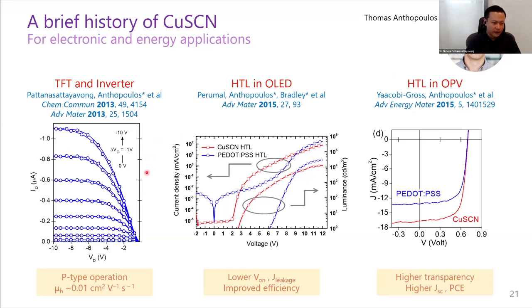It shows a very good field effect, can be used in thin film transistors, and also basic circuit components. And also with the postdocs in the groups back then, we also demonstrated the use of CuSCN as a PEDOT replacement in OLEDs and also in OPVs. As I mentioned at the beginning, the very favorable energetics give them very good performance.